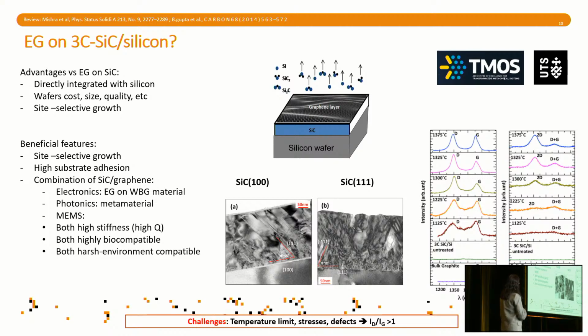Last but not least, you can epitaxially grow silicon carbide on silicon, but unfortunately, the lattice mismatch is more than 20%, such that if you do a TEM section, you will find that the layer is absolutely very, very defective, as you can see here. And of course, if you start with a defective template, your epitaxial growth is going to have to deal with those defects. All that you will obtain is a very defective graphene, and possibly not even a continuous graphene. So that is challenge number one.